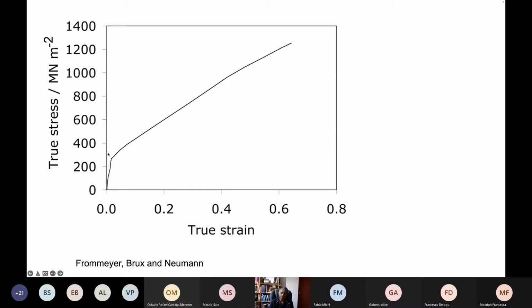Yielding, the yield strength in this particular case is really quite small. It's about 300 megapascals. But you can continue the deformation until the strength exceeds 1.2 gigapascals and maintain an elongation of something like 60%. So this is quite a remarkable combination of properties, an elongation of 60% and a strength of 1.2 gigapascals. But it starts off at a low yield strength, and then it looks like there is a steady work hardening rate as you continue deformation.